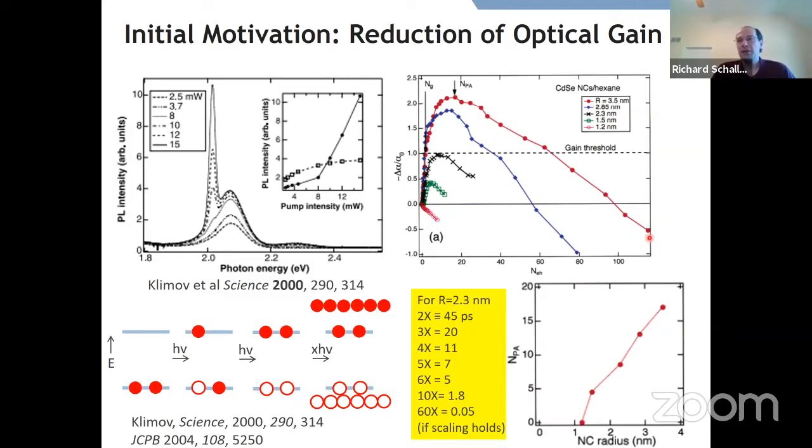and it can decrease pretty slowly, like what's shown here for the largest nanoparticle. But as you go smaller and smaller, you see that this is a pretty important effect that was going across the different systems. And as you go to really small particles, you actually never achieve gain, and instead this turnover of gain to decreasing is at smaller and smaller powers. And so some of the thought there was that maybe phonons in these smaller systems dominate the electronic structure more and more. You have fewer atoms that are easier to cause expansion and contortion of the lattice. And so therefore maybe the electronic structure is getting botched in some way that is not desirable.